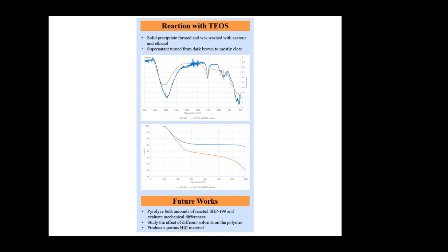After reaction with TEOS, our material retains 20 percentage points more mass. Additionally, between 700 and 1300 Celsius, the TEOS product is remarkably thermally stable compared to the SHP-199 on its own. This is a great starting point, but we still have more to do. I would like to pyrolyze bulk amounts of each of these reacted polymers and evaluate the mechanical differences between them.